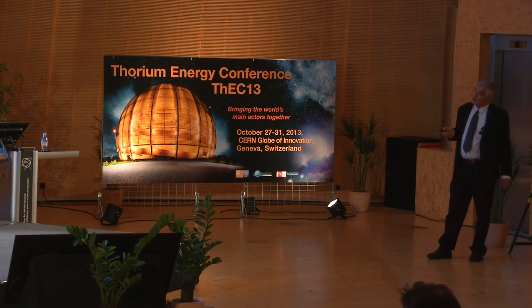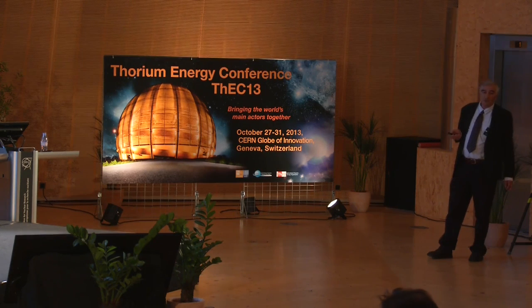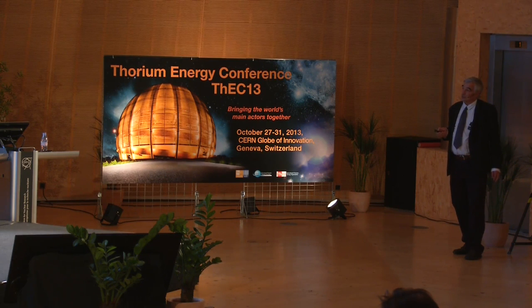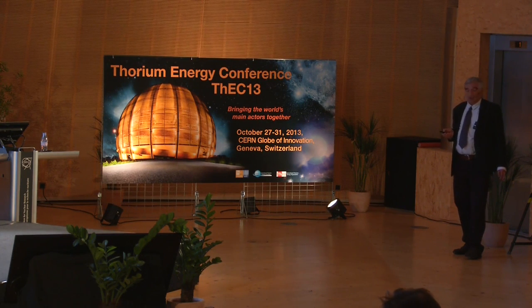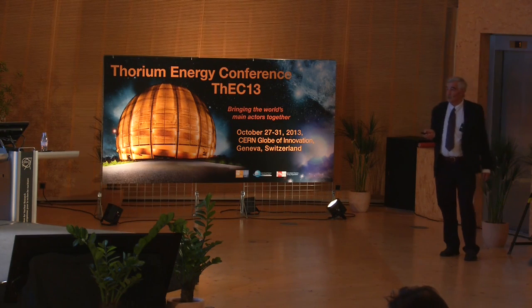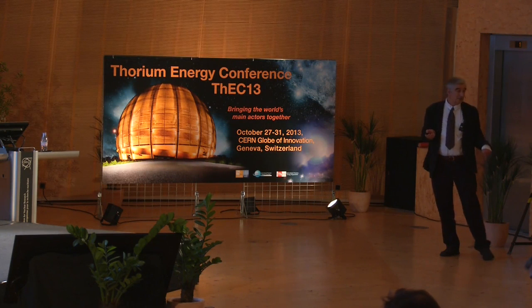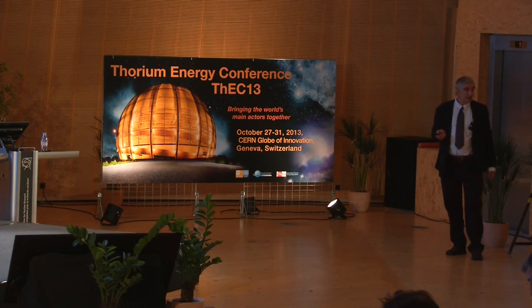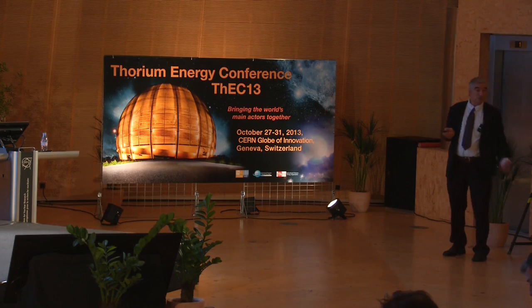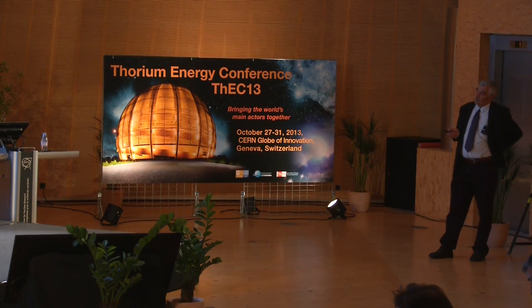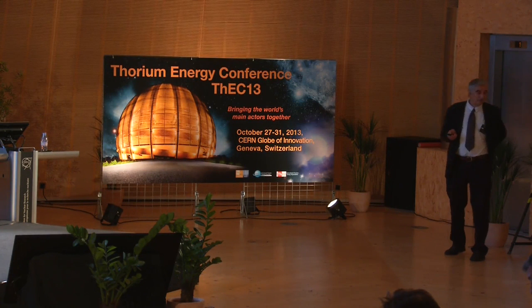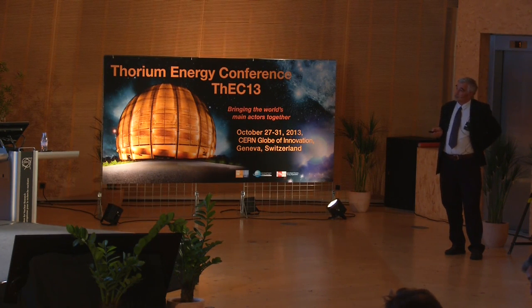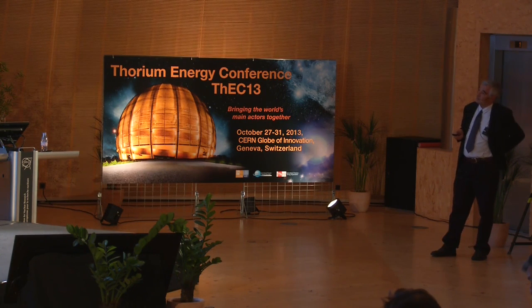About the chemical and radiochemical analysis of LBE, I won't go into much detail, but there was very important work performed essentially at PSI. We have some predictions, and particularly we have tried to have a qualification with an experiment which was performed here at CERN, in the Isolde facility, on irradiation of LBE, in order to establish and predict the production of radionuclides. About results on LBE samples, of course, there were a lot of products, and particularly results on bismuth, on gold, on lutetium, distribution in the MEGAPIE target.